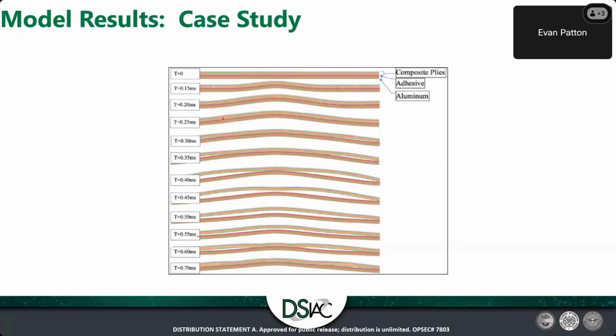And in this figure here is when you actually see an initial delamination site here, which progresses throughout this entire composite ply, eventually completely delaminating, as well as having extensive delamination throughout the composite until it finally settles back into its final deformed state. That is, for lack of a technical term, fluffed up, where all these composite plies are kind of delaminated, just kind of laying on top of each other.